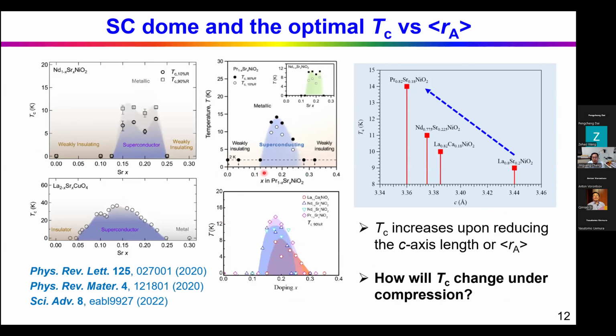Some follow-up studies have established a dome-like superconducting phase as a function of the hole doping. So this phase diagram is similar to the hole-doped cuprate, with a dome-like superconducting phase. But the highest Tc for the nickelate is around 10 to 15 Kelvin. It's much lower than the cuprate.